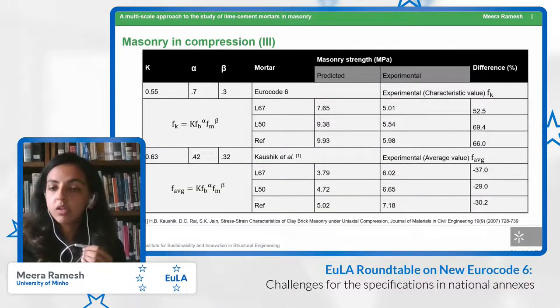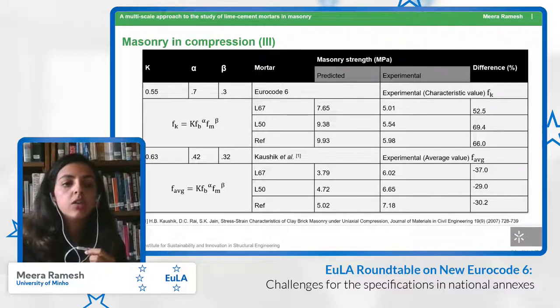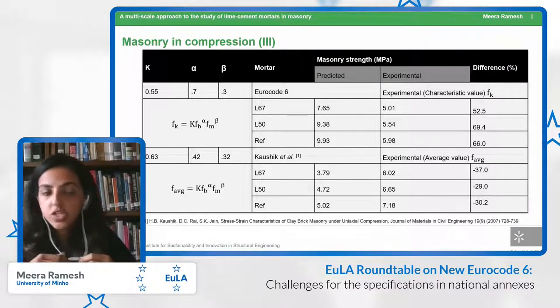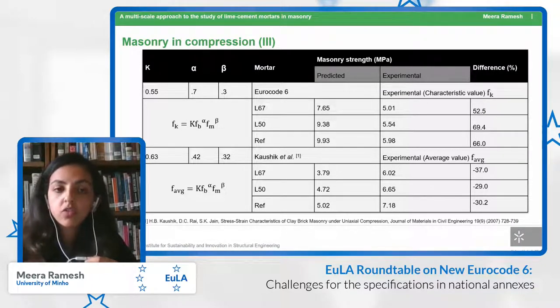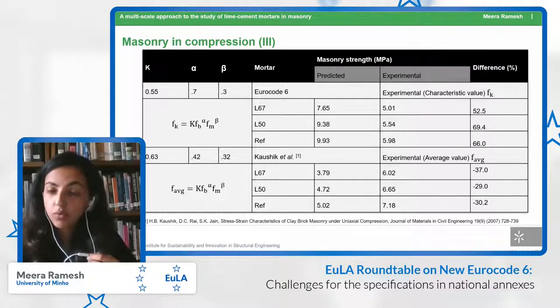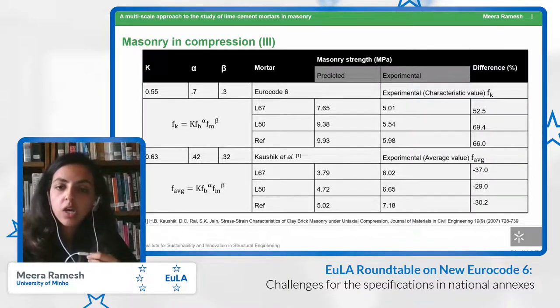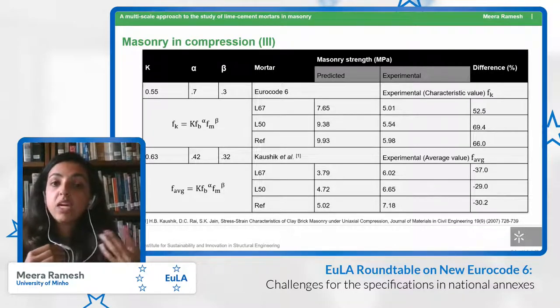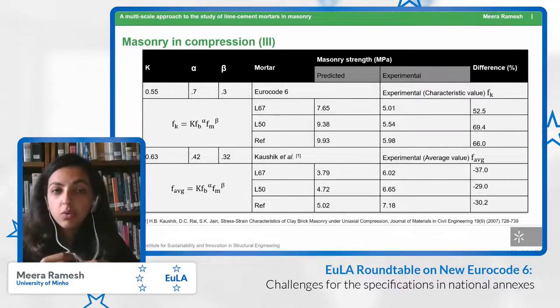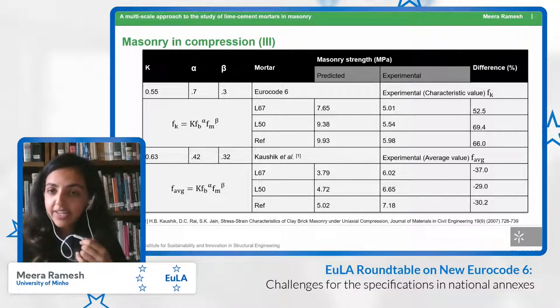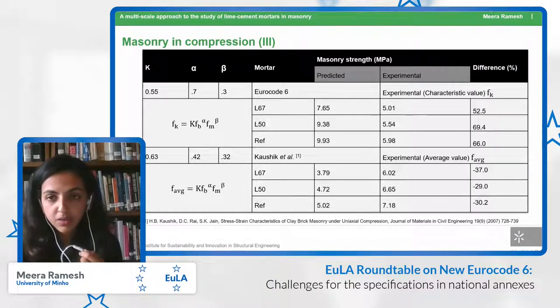We also tried to use our experimental values and compared them with what the Eurocode recommends. The Eurocode recommends an equation which uses the strength of the brick and the strength of the mortar to estimate the strength of masonry. And we found that when we compared our experimental values with the Eurocode values, Eurocode 6 significantly overestimated experimental values.